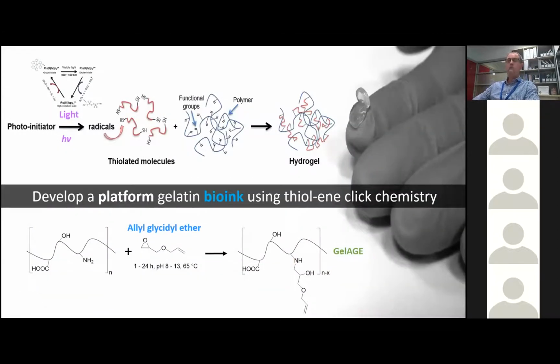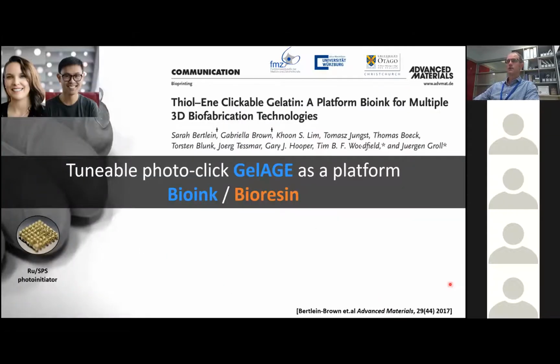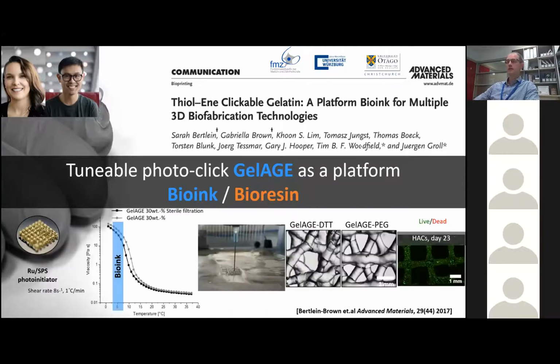So one thing I wanted to try and focus on, of course, is these different platform bioinks and more of this step growth polymerization. So we've been working with allylated gelatin. So again, we've termed this GelAGE. So again, what we're trying to rely on as part of this is whether we can look at developing a tunable photoclick version of these allylated gelatin, and whether they have inherent properties which mean they can be used across multiple different types of platforms. So again, this essentially relies, in terms of cross-linking, on the dimerization of different thiols, again with different reactive carbon-carbon or ene groups within these hydrogels to generate a very homogeneous and complete cross-linking process.